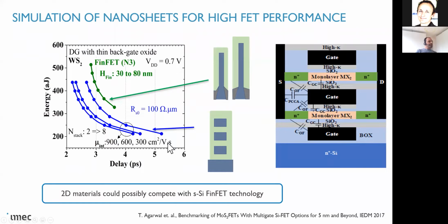So again, you see energy delay. And what is in there is some assumptions. We assume that we have a contact resistance of 100 ohm. Some of these things are not fully realistic, but at least these are numbers that we need to reach to become competitive with N3 FinFET simulations. And then you see that the number of stacks is between 2 and 8 sheets of 2D material on top of each other.